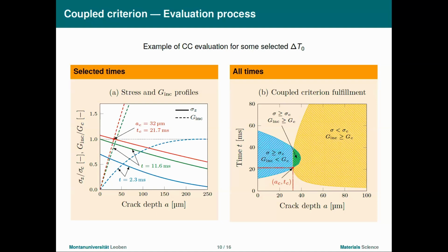So let's look at it. The blue case is after 2 milliseconds. The stress is normalized by the strength and fracture toughness. So the strength is never reached, nowhere. The same goes for the energy release rate. It's almost overcoming the fracture toughness, but not yet.